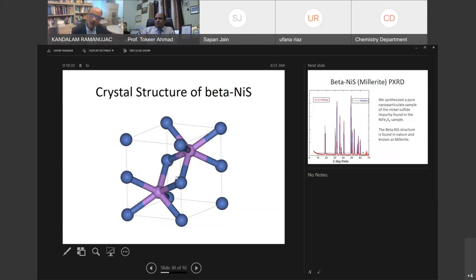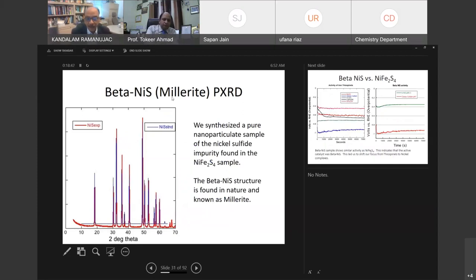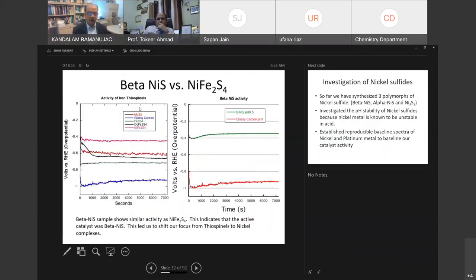So what we did was, why not make this beta form of nickel sulfide and see if it has electrocatalytic activity. Here is the X-ray powder pattern. Millerite is the name of the natural mineral that is nickel sulfide, which has the same crystal structure. So we were able to replicate that synthesis and we did the nickel sulfide work. Here is the comparison of the thiospinels versus nickel sulfide. On your right-hand side, you see the overpotential, which started at 0.4, and in fact improved to almost 0.35 and was very stable. So nickel sulfide is far superior to even nickel iron sulfide.